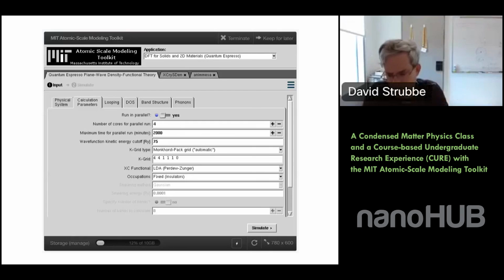And the numbers I'm quoting just multiply by a factor of 1,000 to 1,000,000 for what you can get to with classical rather than quantum ones. In terms of limitation for research, it kind of depends what you want. People's ambition just keeps on expanding as computer power grows. So people are trying to look at something like, for example, crack propagation, which I think is a classic example of something that requires millions of atoms to make anything sensible out of it. And so people have been doing more realistic, more complicated simulations of that over time.